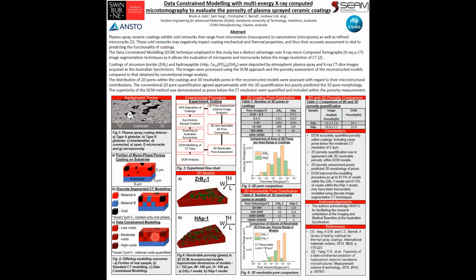porosity with a moderate CT resolution, which was 5.4 micron. Coatings of the materials zirconium boride and hydroxyapatite were deposited via atmospheric plasma spray, and X-ray CT slice images acquired at the Australian Synchrotron Imaging and Medical Beamline, utilising the Ruby detector. Samples of the coatings also underwent a 2D pore assessment via image analysis.